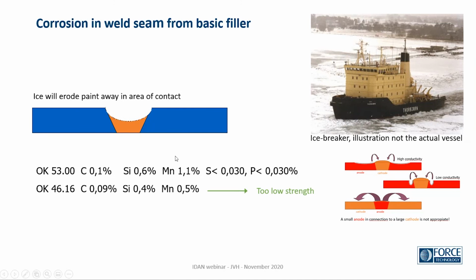But the reason for the problems was that a basic electrode was used with a relatively high amount of silicon and manganese, which caused some hardening elements in the microstructure, which would be noble to the structure around them, and by that the weld metal was losing its corrosion resistance. And of course, the ship hull was painted, but it is especially a problem for icebreakers that the paint would be eroded, worn away by ice, opening for corrosion in the steel and the welds.